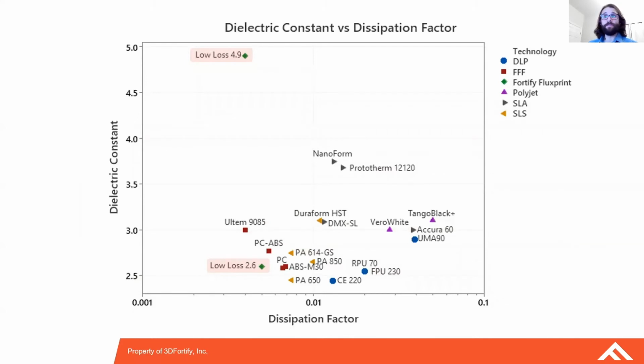Revisiting this chart from the beginning of the presentation, we can see where these two low-loss photopolymer materials fall on the chart. These materials exhibit competitive loss performance when compared to both the thermoplastic fused filament fabrication and SLS materials. This 4.9 material, which will continue to be in development for a few more months, breaks the paradigm of polymers living in the 2 to 4 dielectric constant space. This dielectric polymer offers incredible advantages when designing monolithic, high contrast refractive index devices.